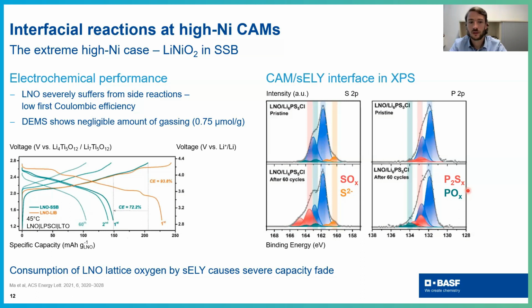But the problem is that your lithium nickel oxide is really evolving towards nickel oxide at the surface, and this is not a conductive layer, which is resulting in such poor performance even in the first cycle. So you see these interfacial phenomena which are destroying your cathode active material already in the first cycle.